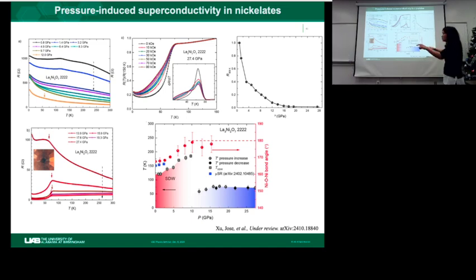So you mentioned that we have this rising tail that we couldn't understand. My theory was this is filamentary, and there is a competing phase causing this rise of resistance, because before that we also have a semiconducting state, and then there's a semiconductor to metal transition. But you see here, especially in this curve, there is a sharp rise after a so-called SDW phase, and I think there could be some competition of superconducting phase and non-superconducting phase. Whatever that non-superconducting phase is also very critical.